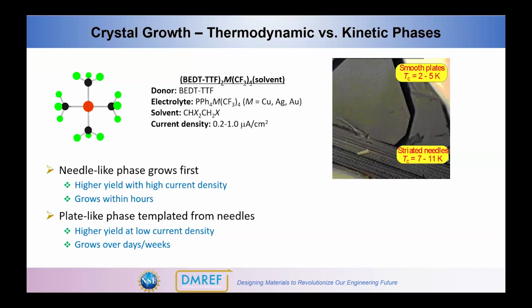And so we took this one with the metal CF3 anion and crystallized it in a trichloroethane solvent. When we looked at the crystals that we had, we noticed they're both plate-like phases and needle-like phases. What we observed was that the needle-like phases grow first. So if you turn up the current a lot and grow it fast, you got a lot of the needle-type phase. And if you grow them slower and with more time, then you get more of the plate-like phase. One of these is the kinetic phase, one is more the thermodynamic phase. By controlling the current density, et cetera, one can control what phase you get.